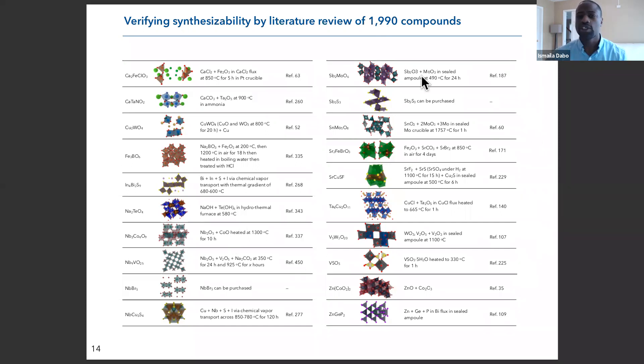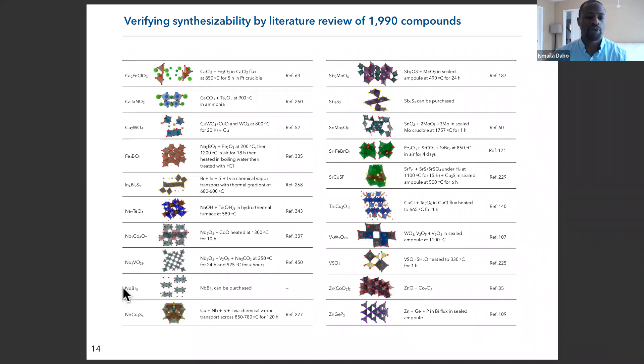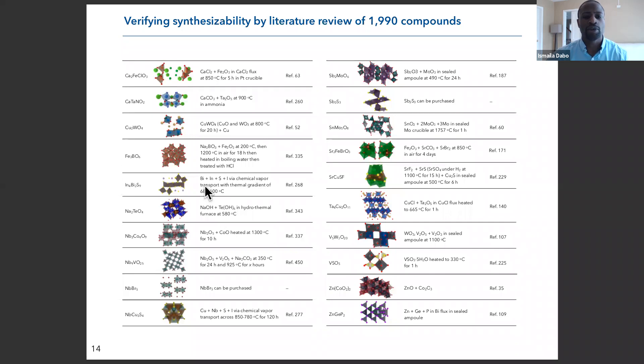They assembled a table — a portion of which is shown here — telling us for each compound how it can be realized synthetically in the lab. For some, like certain niobium bromides, you can simply purchase them. Others can be made by thermal furnace synthesis. For some, you need more advanced techniques such as chemical vapor transport with a specific thermal gradient in order to achieve the indium-bismuth sulfide material.